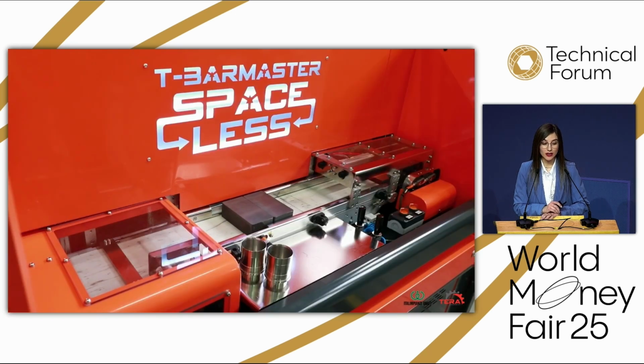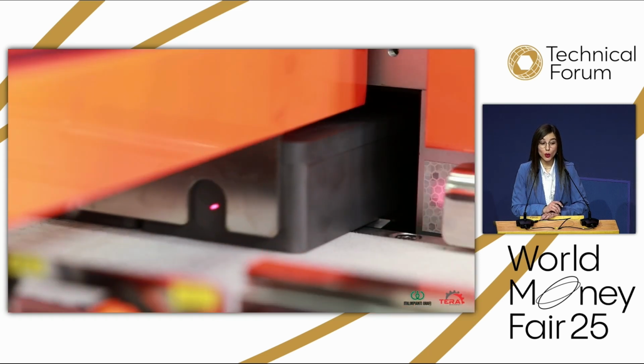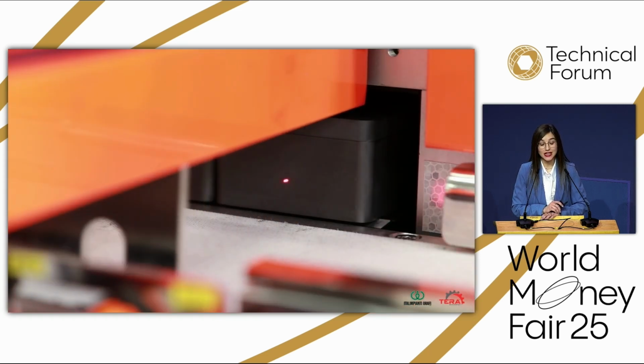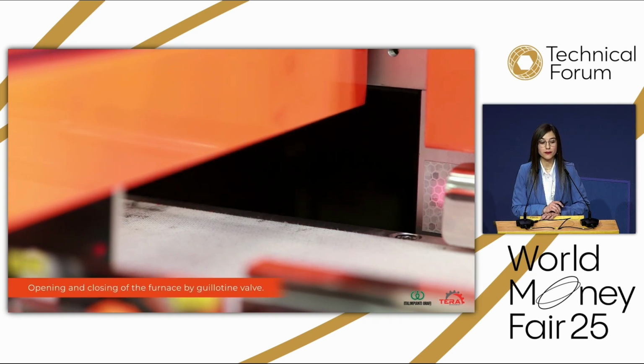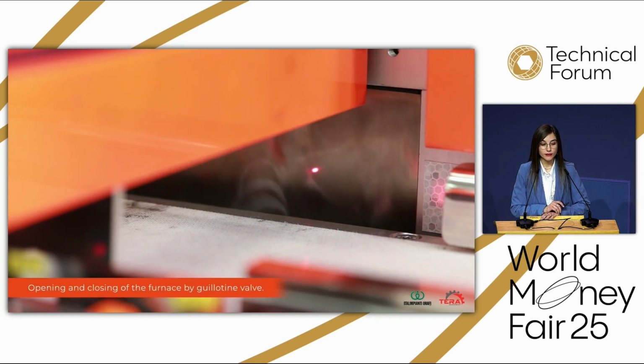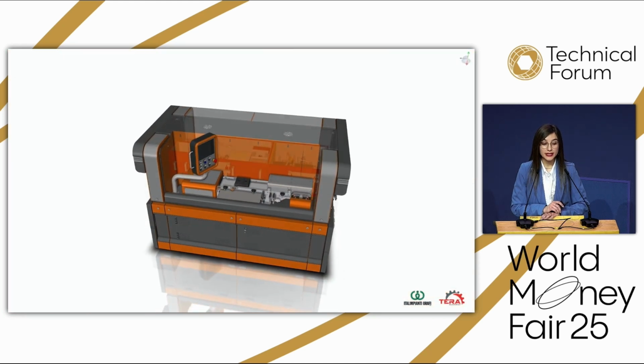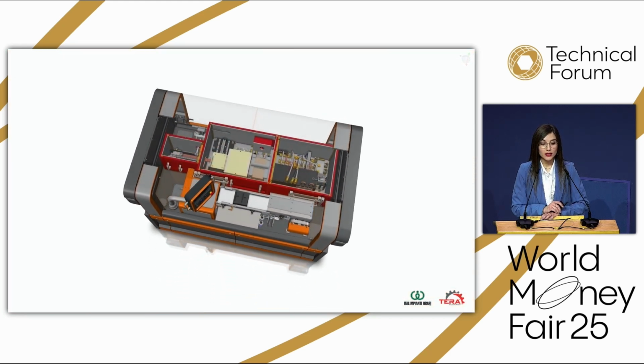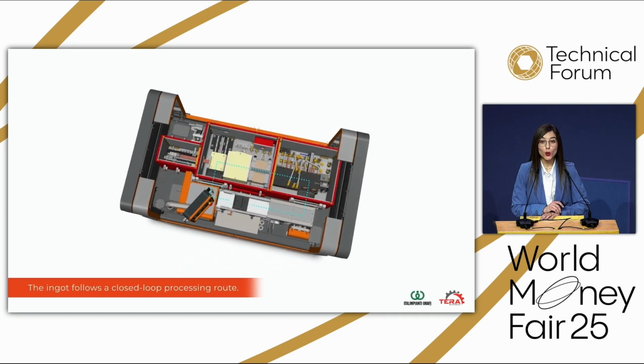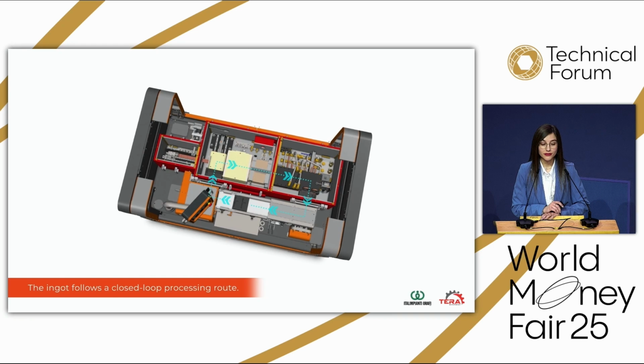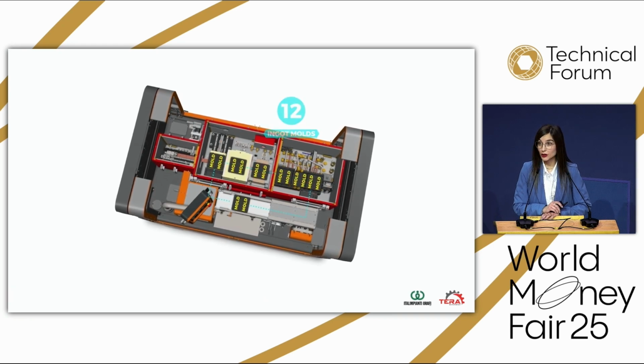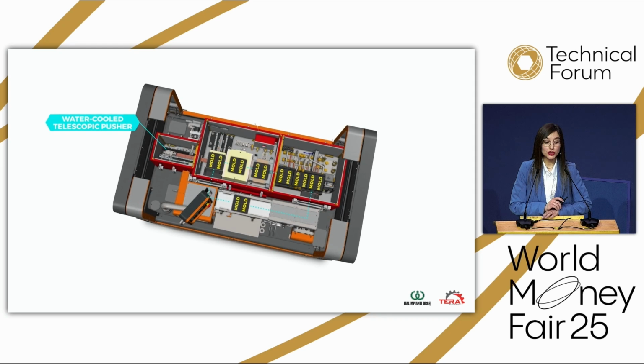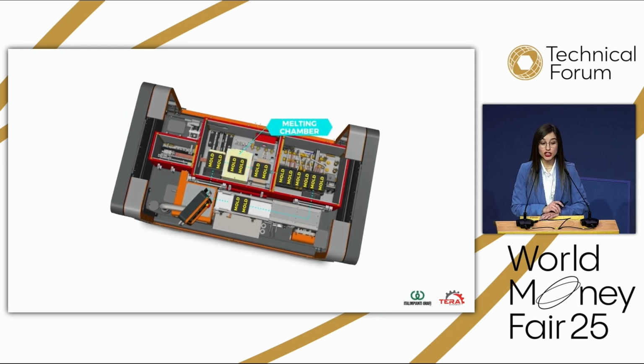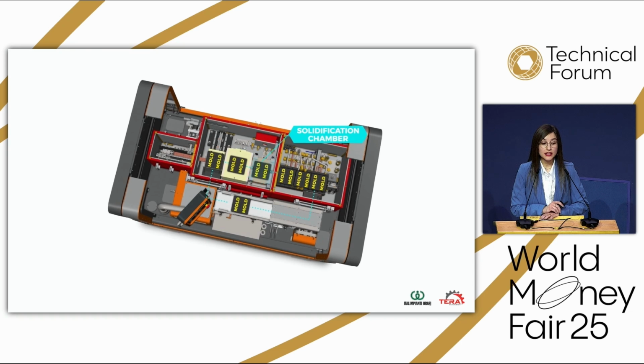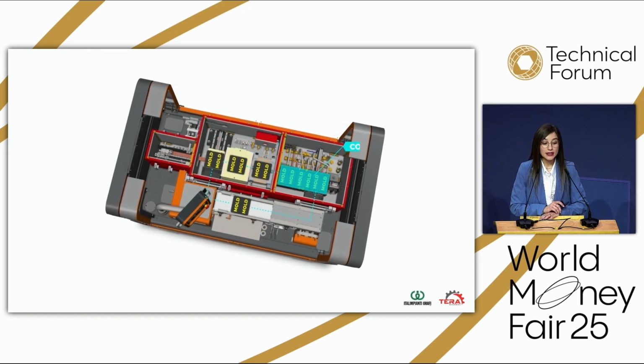And now the process can start. So the guillotine valve opens, allowing for the ingot mold to enter the furnace. So they are pushed inside the furnace and then the guillotine valve closes. Here we observe the interior of the furnace, whereby the ingot molds follow a perfect closed-loop path. The furnace fits 12 ingot molds. So first, the telescopic pusher moves the ingot molds toward the melting chamber. Subsequent pushers then transfer them to the solidification plate and to the cooling tunnel.